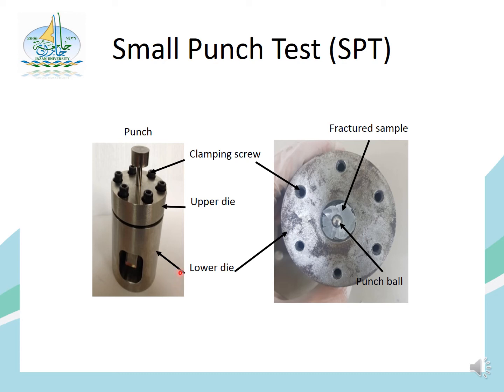The diameter of the small punch tested specimen is around 20 millimeters, with a thickness of around 2 millimeters. Also, the small punch test in this work is used to describe the effect of the nanoparticle weight percentage for the aluminum oxide. It started from 0.5 percent by weight, then 1.5 and 3 percent by weight, and the stiffness of the composite specimen. Also, we are trying to extract the load displacement curve for this small punch test.